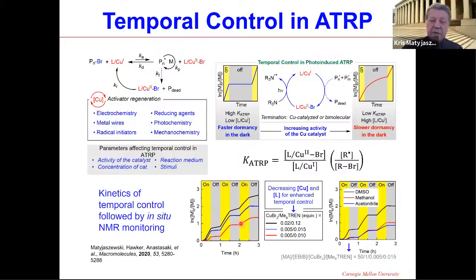It's a project which was run by Greg's group, Athina Anastasaki, but also Sajjad, who is chairing this session. And we observed that sometimes when you switch the light off, the reaction can stop nearly instantaneously, but in some cases it can continue for much longer. So this is a little bit special process because in this photo ATRP, everything is based on photoreduction. So we reduce copper 2 to copper 1 by light in the presence of some electron donors. And if you have a large enough copper 1 accumulated, in that case, this termination process cannot stop the reaction and it can continue for a longer time.